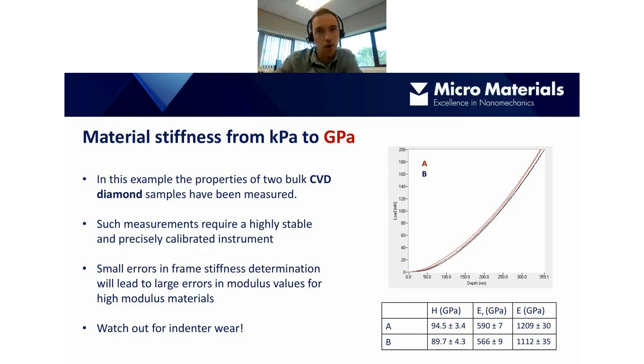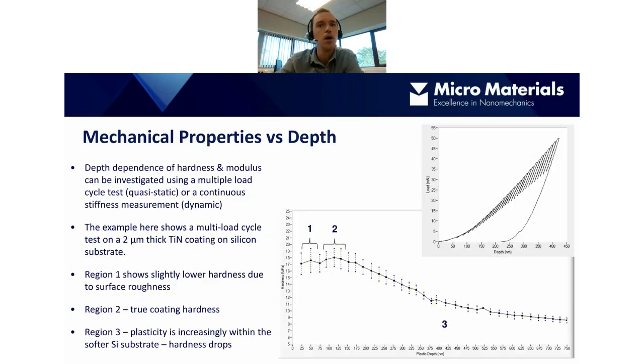Of course, when we're indenting materials as hard as this, we need to watch out for indenter wear, especially with samples like this, very hard and also quite rough, these synthetic diamond coatings. It can be a bit of an indenter graveyard. Another common application of nanoindentation is to measure mechanical properties as a function of depth. This is particularly useful for coated samples, thin films and coatings. There are different ways we can do this. Often it's done with a load oscillation technique, but it can be done with a standard quasi-static technique, such as the one you can see here.